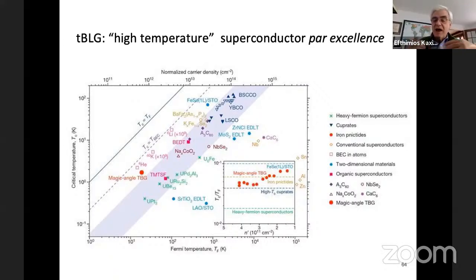So it's not possible to change the absolute value of the temperature easily in graphene, but hopefully we can do it in other systems or with multilayer graphene. As I showed you, the temperature in multilayer graphene is a factor of 3 higher. So this is around 1 degree. In bilayer, in trilayer, it's a factor of 3 higher. So it's really strongly correlated systems, and possibly also by intercalating other atoms, by using techniques for doping graphene with different types of intercalation atoms. So we have hopes that this could lead to raising the temperature in pure graphene due to the nature of carbon atoms. Again, the absolute temperature is low, although the scaled temperature, which is a signal of the strength of the correlation, is quite high.